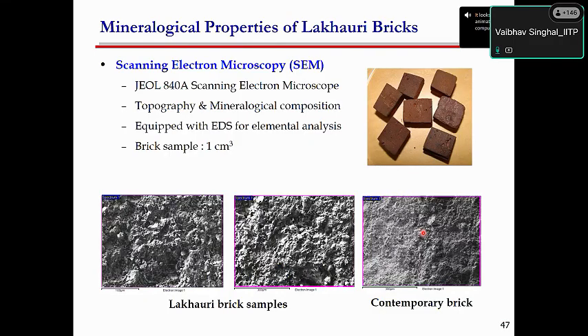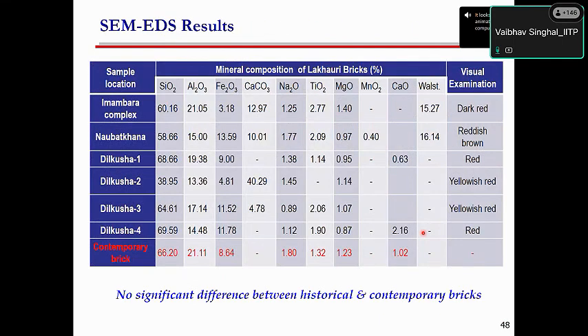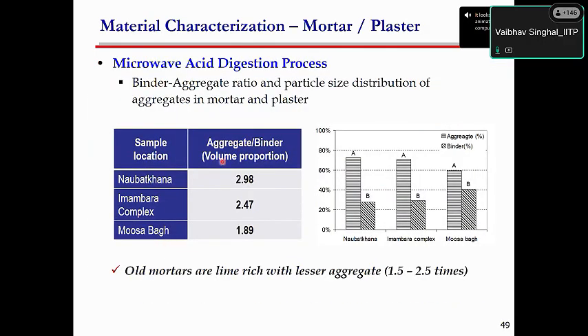Then we moved to the material characterization to know more about the bricks, what their compositions are, and compare them with the contemporary bricks which are available these days. We found that the bricks in the Mughal era and the bricks which we currently use are nearly the same. There is not much difference. In the binder aggregate ratio, we found it is a lime mortar, a lime-rich mortar. The ratio is found to be 1:1.89 to 2.98, so about 1.5 to 2.5 times aggregate to lime binder ratio we have seen.